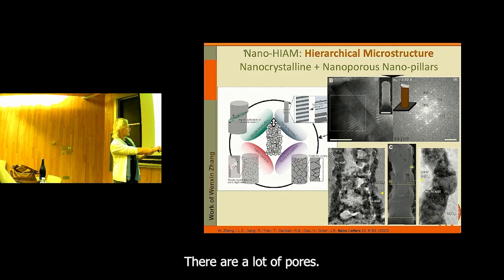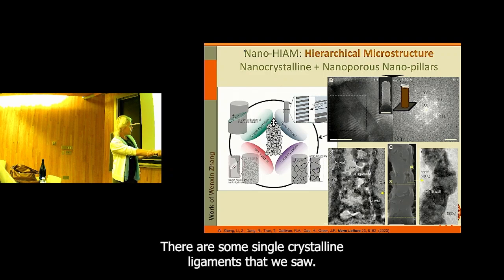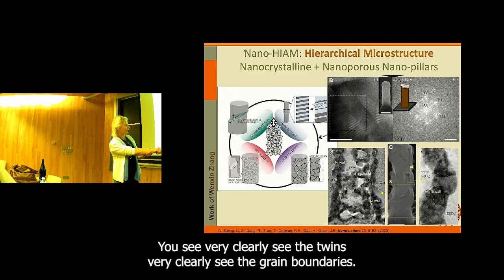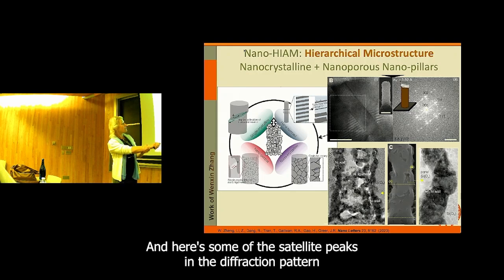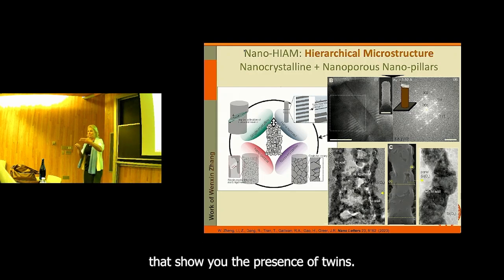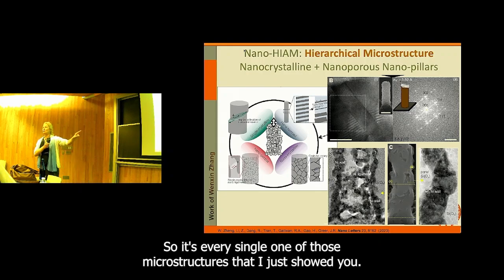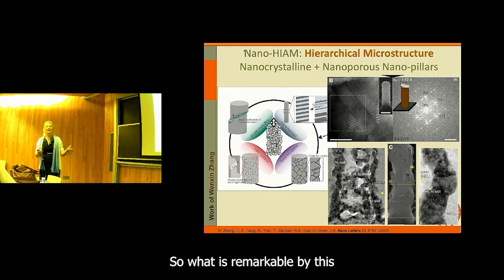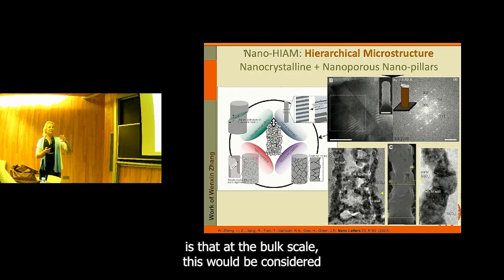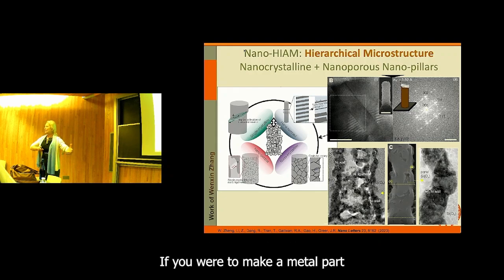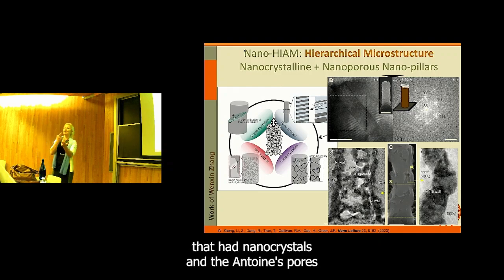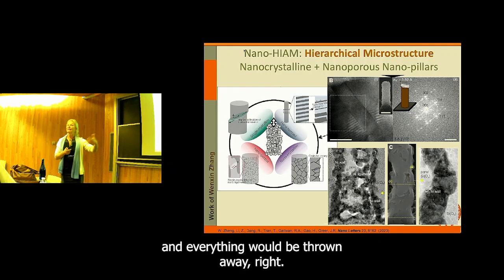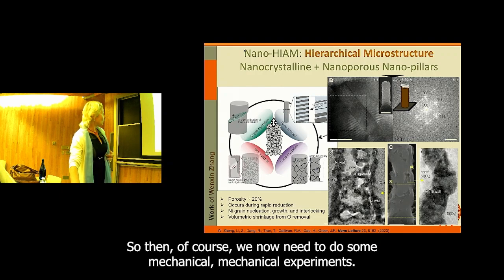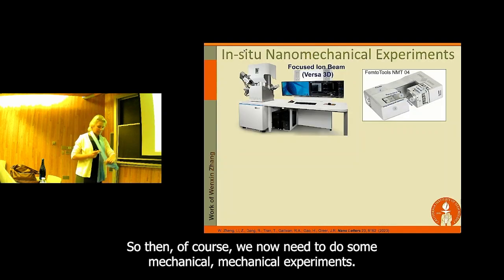There are a lot of pores. There are some single crystalline ligaments that we saw. Here's the nickel wall right here. You can very clearly see the twins and the grain boundaries. And here are some of the satellite peaks in the diffraction pattern that show the presence of twins. So it's every single one of those microstructures that I just showed you. What is remarkable is that at the bulk scale, this would be considered a very crappy microstructure. If you were to make a metal part that had nanocrystals, nanotwins, pores, and everything, it would be thrown away. So of course, we now need to do some nanomechanical experiments.